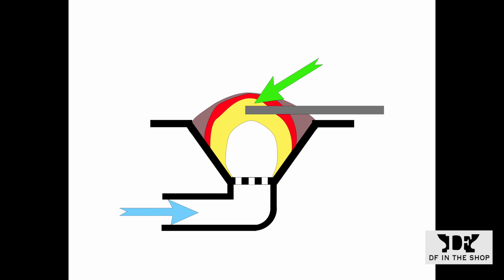So if this fire looks familiar to you, it's probably the reason you're only getting welds to stick about 20 or 30% of the time at best. The border between the oxidation zone and the neutral zone is just too close, and it's probably always moving. If the oxidation zone drops a little bit, you're going to get welds to stick, and if the border moves up a little bit, nothing's going to work for you.